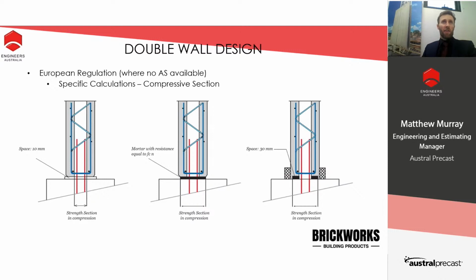In the event that the space under the panel cannot be achieved, but we still want to have the full compressive strength of the panel, we can use mortar on the joint as per the middle drawing here. So in that case, if the joint was less than 1.5 times diameter, a mortar bed could be applied either pre or post pouring of the panel in order to provide the full compressive section of the wall. Our preferred option at Austral Precast is to reduce the use of grout, not only due to the cost on site, but also due to the inherent nature of relying on workers on site to make sure this is correct.